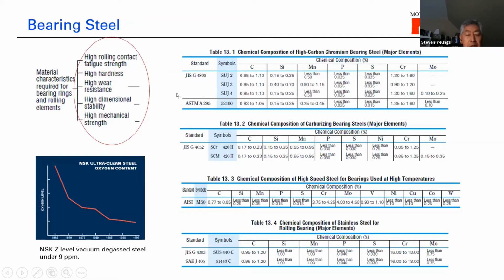But one thing for sure, bearings still have to be clean. They are very pure. Over the last 40 years, the manufacture of bearing steel has been refined so much. The oxygen content has been kept so low. Nowadays, in the year 2000, NSK, as far as the steel goes, maintains what they call the Z level. They can keep the oxygen content way under the 9 ppm mark. So for some of the key major manufacturers of bearings, keeping the steel as clean as possible is one of the major goals in order for the bearing to have good fatigue strength.